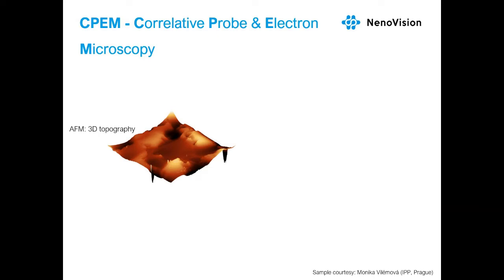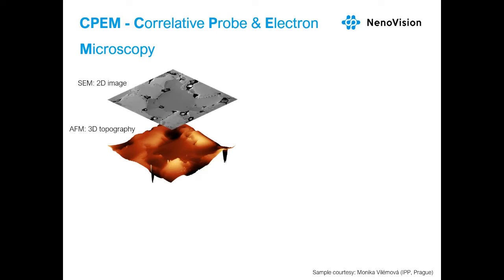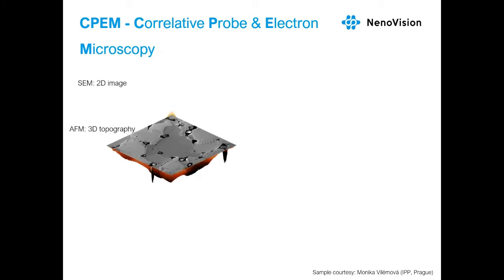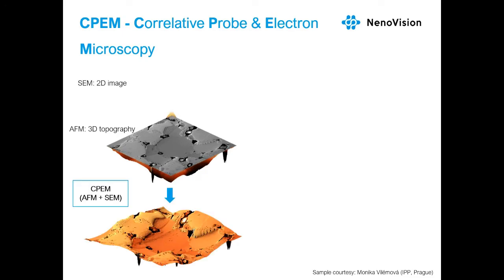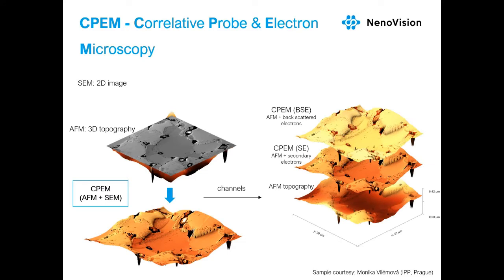This technology is unique to LiteScope and was developed for seamless data correlation. As we can see, the captured AFM and SEM images are subsequently correlated into one three-dimensional CPEM view. The CPEM view can contain multiple channels, as shown on the right of the slide, of backscattered electron and secondary electron. For this particular application, the AFM topography was correlated with the signals from secondary electron and backscattered electron detectors. So the information from SEM was extended into the third dimension using the AFM topography.